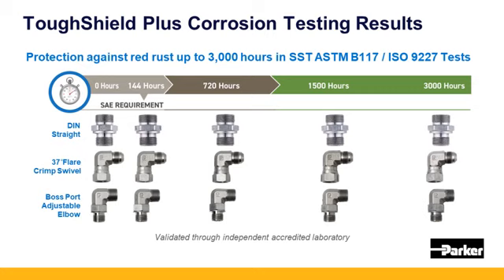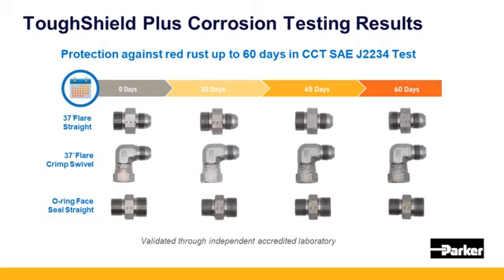But with Toughshield Plus, no base metal corrosion up to 3,000 hours. The only corrosion you will see here is some of that white haze, but again, counterintuitively, that actually is good and helps further protect the product from further corrosion, as Yindong had mentioned.